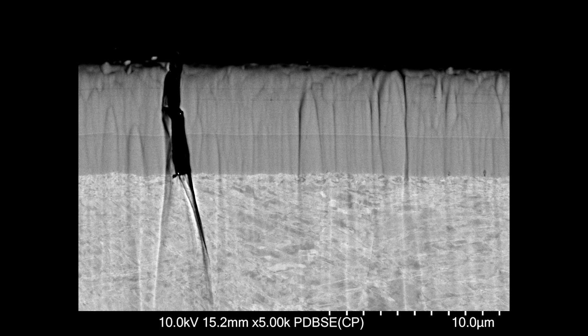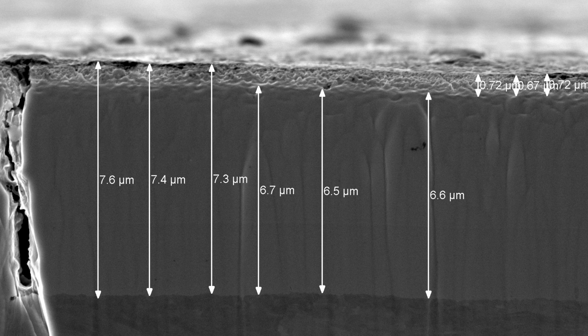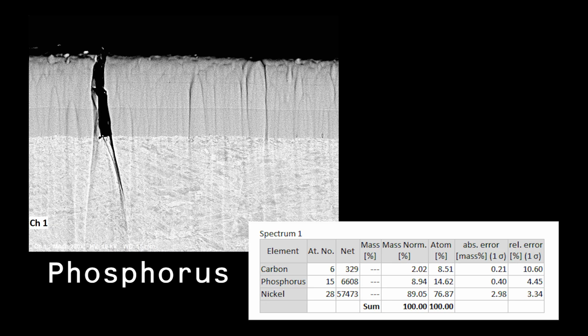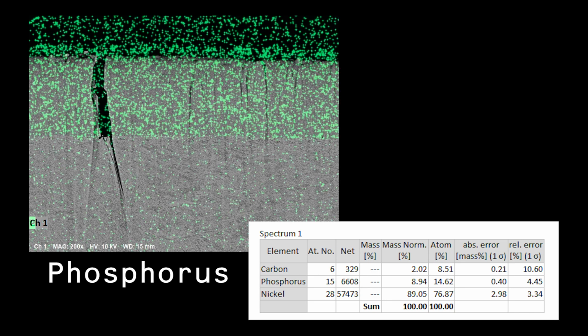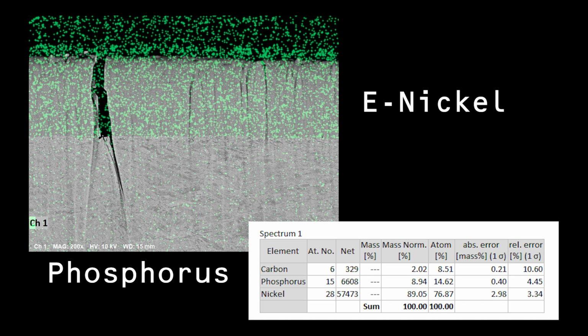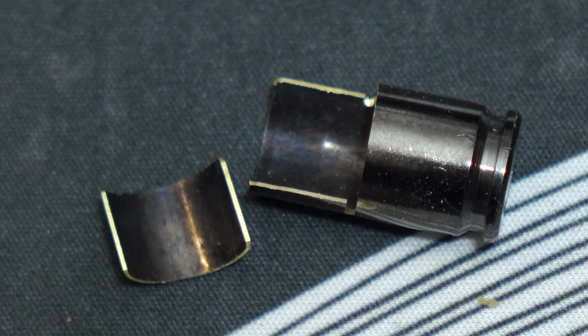And my good EDS detector is in the shop right now, so I couldn't get really into the ultrafine detail here with these layers. A couple of things that we can observe here, though, is that this layer is a bit thicker than the nickel layer on the bullet, at about 6.5 microns. And it also contains about 9% phosphorus. Now, that is super important information, and it is telling us that this is most likely a material called E-nickel, which is a type of coating that can be deposited on parts, but doesn't require an electric current like electroplating does. Now, while that's good to know and all, it doesn't really explain the black coloration of this case.